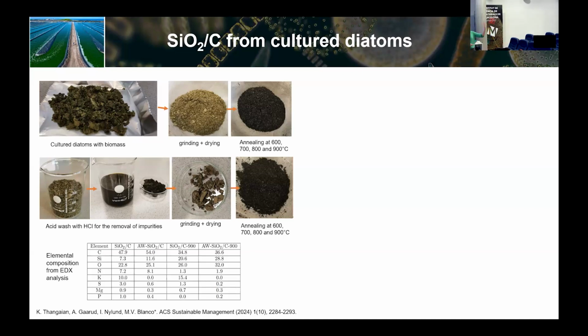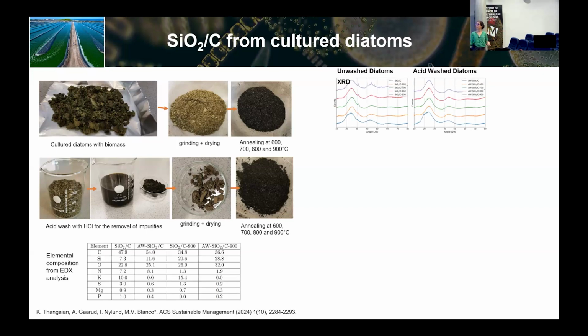So when we did the annealing at different temperatures for both cases, non-acid wash and acid wash, we saw these are the exact results that, of course, at the beginning, material looks amorphous. But when you start increasing the temperature of annealing, you can see how the impurity peak starts to emerge because they start to become more crystalline. And then we can actually see what these impurities are made of. Calcium oxide mostly.